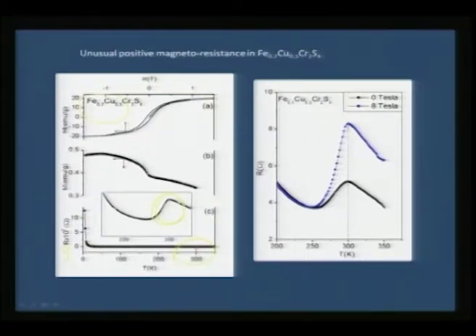So, in such a case, if you take this particular composition and measure the resistance both at 0 Tesla and at 8 Tesla, you can see that there is a huge rise in resistance of this order, which means more than 70% magnetoresistance is observed above room temperature for this particular composition. This is reported for the first time in the literature.